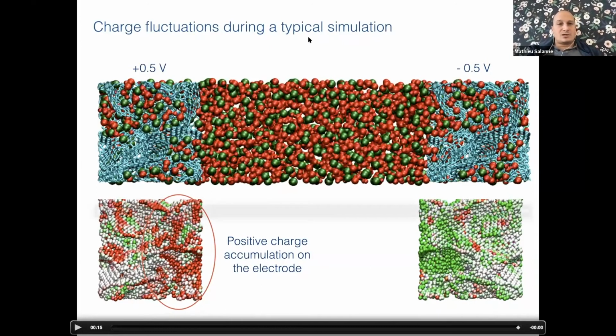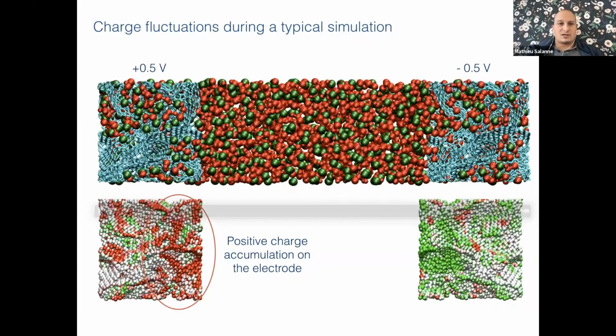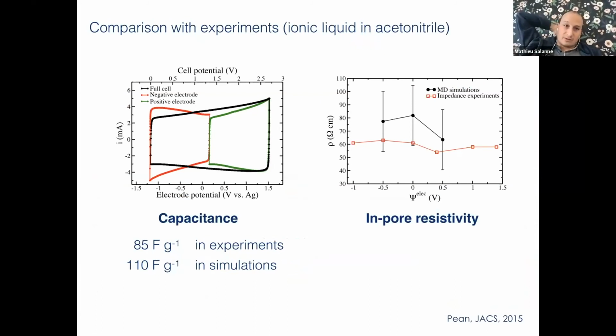And so does this simulation setup work well? To check this, we compared a system with some experiments. The main quantity which is measured is the amount of charge per gram of carbon, and this is obtained through cyclic voltammetry, as you have an example here on the left. The typical value which is obtained in experiment is about 85 farads per gram for such systems. In our case, we have 110. So I think this is a good agreement. We have 20% of error at most. And so this means that we have the good concentration of ions inside the electrode. We have the good structure.